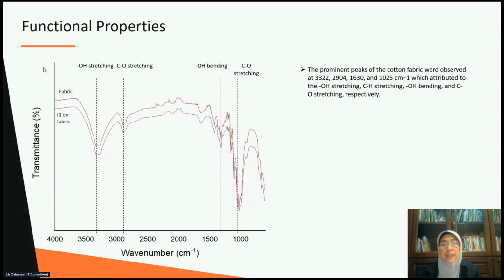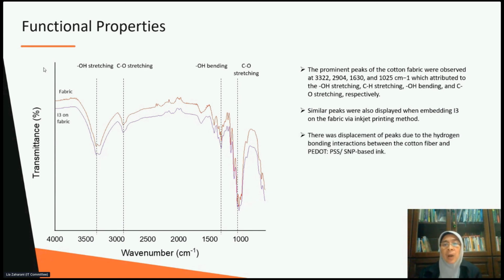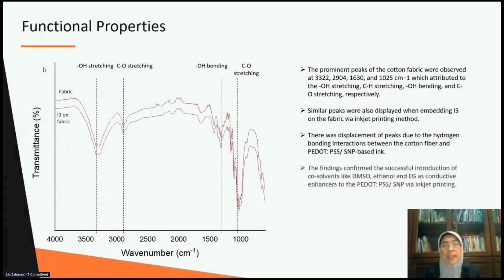Similar peaks were also displayed when embedding ink 3 on the fabric via the inkjet printing method, shown in our article. It is noticeable that there was a displacement of peaks due to the hydrogen bonding interactions between the cotton fiber and the PEDOT:PSS/SNP-based ink. The intensity of the peaks was also decreasing, which is associated with the existence of other components present in the sample. As a result, the findings confirm the successful introduction of co-solvents, for example DMSO, ethanol, and EG, as conductive enhancers to the PEDOT:PSS via inkjet printing.